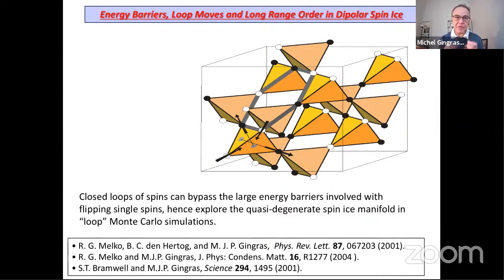I don't have the time to go into the details of that. The problem is that once you go to low temperature and the system gets into a situation where the nearest neighbor correlations, the ice rules, two spins pointing in and two spins pointing out, develop, the system gets trapped into a manifold of very low energy states, which obey the ice rules, but which are separated by large energy barriers that cannot be activated by thermal fluctuation. Remember, there's no quantum tunneling going on, because these spins are Ising-like. These are classical systems. All equilibration must proceed through thermal excitations.